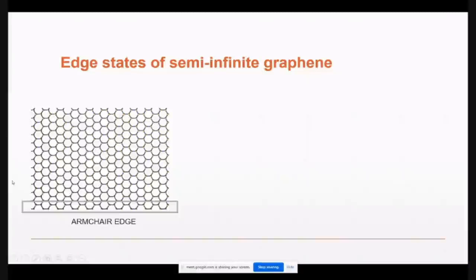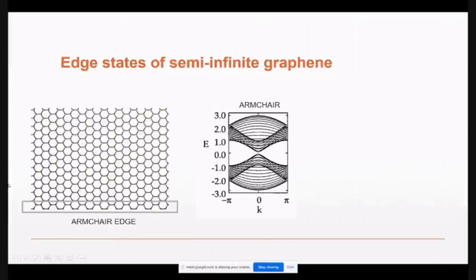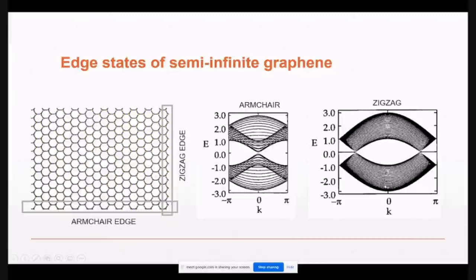For example, if you have an armchair edge, you will get a gap structure, which is at k equals 0, there is a gap. Whereas this is the zigzag edge, and in the zigzag edge you get a completely different behavior, which is a zero energy state. There is one particular band which essentially becomes zero energy, and this is very similar to what happens in topological systems. But this is not topologically protected, because if you create lattice defects, then these zero energy states go away.